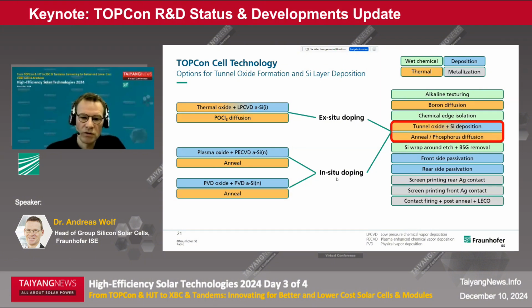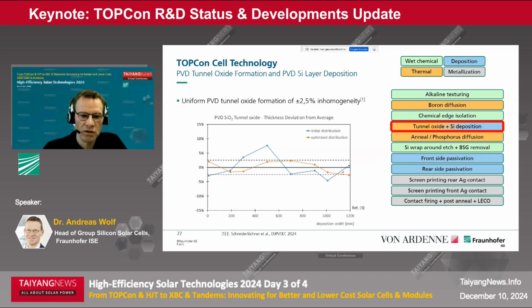Regarding the PVD technology, we do some developments with our industry partners. One essential part is to get a uniform oxide thickness of the interface oxide through your industrial process. And here you see the oxide thickness relative to the deposition width of the sputtering system, and here we achieved a quite uniform result over the whole width of the sputtering system, showing that there's an industrially feasible process.